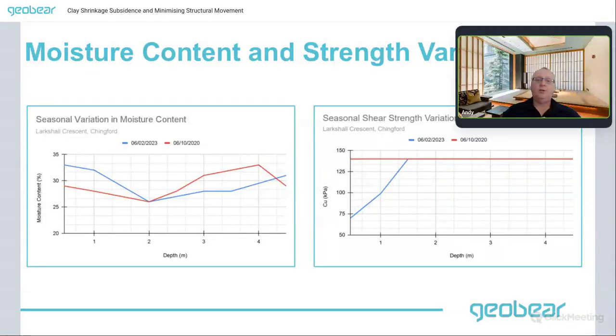Here is a plot of moisture content and a plot of seasonal variation in moisture content. What you can see, particularly on the graph on the right-hand side, is the red line showing the summer conditions, with uniformly stiff soil of 140 kPa at all depths. And yet on the same site, measured during the winter, the shear strength dropped off tremendously to around 70, 75 kPa. So this change is entirely due to moisture content variation. Just the moisture being taken from the soil was affecting the shear strength of the soil.